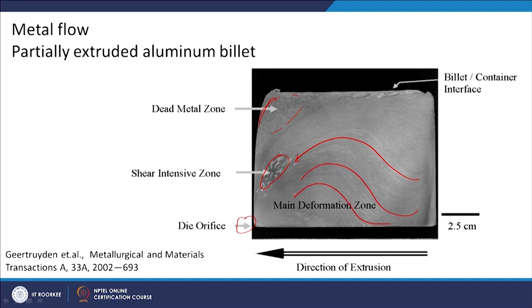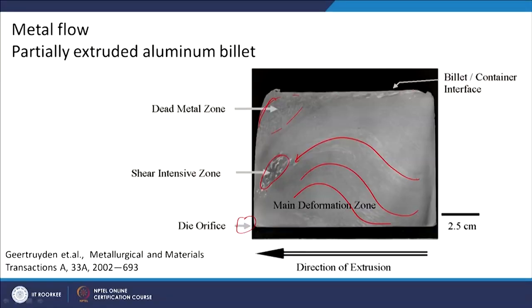So, you can see that in the same extrusion again there is a lot of variation in the microstructure and the strain rate. And at the edge of the billet where it is coming in contact with the die, or the container, because of the frictional effect you can see a lot of coarse grain there. The temperature must be high at that point.